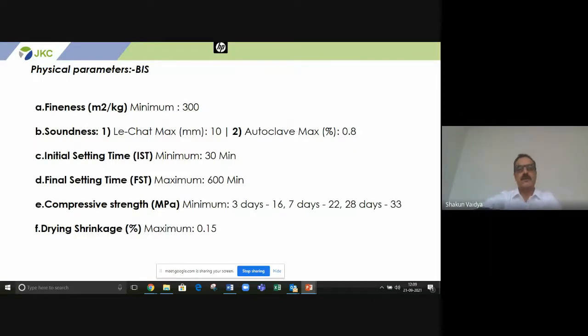The physical parameters of this cement almost match the physical parameters of other variants such as PPC and PSC. I'll show you a chart in the coming slides. It has to have a minimum fineness of 300 square meters per kg. It has to be sound, so 10 mm or autoclave 0.8 is the permitted value in percentage. Initial setting time, the time period after which the hardening should take place, is 30 minutes. Final setting time is 600 minutes. This is the time when the paste or the concrete should ideally lose plasticity and start hardening.